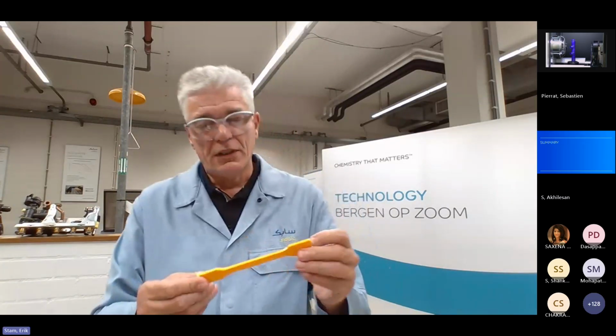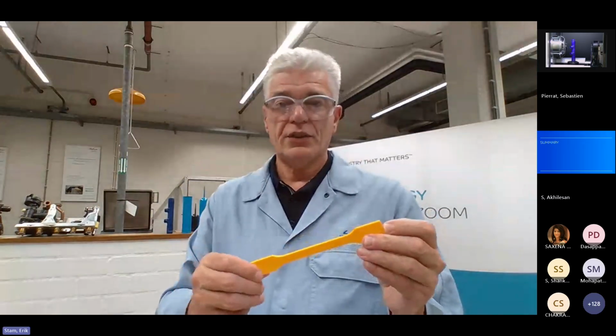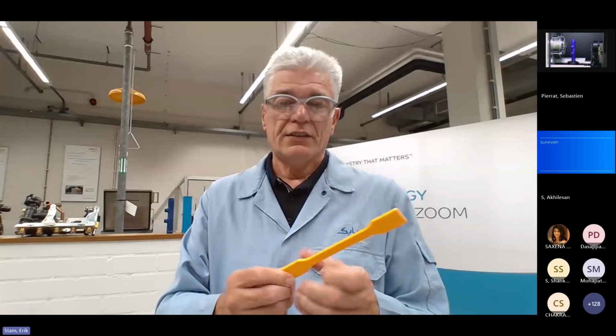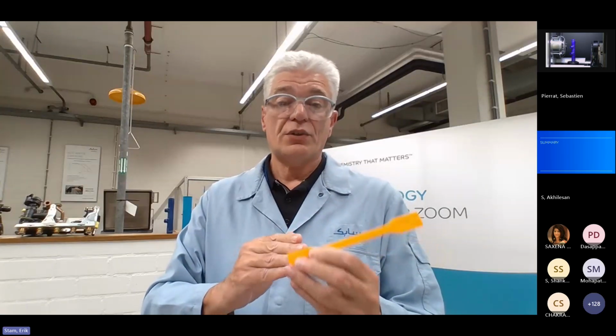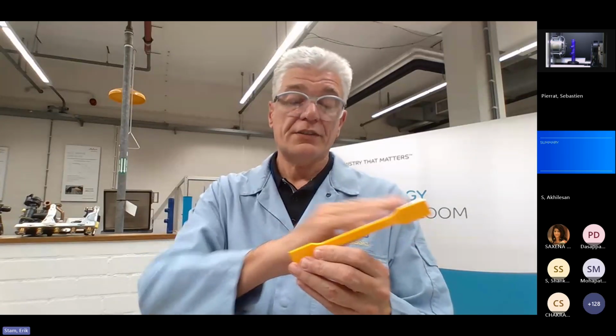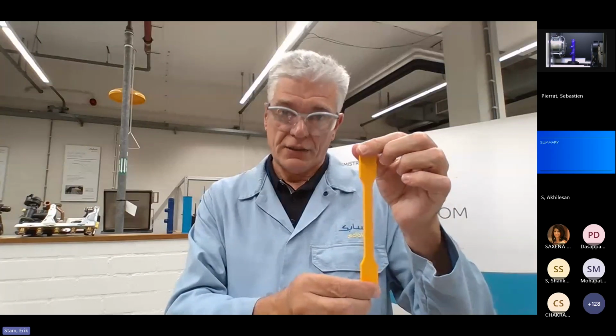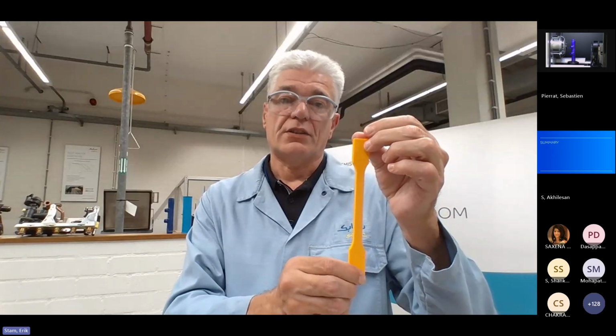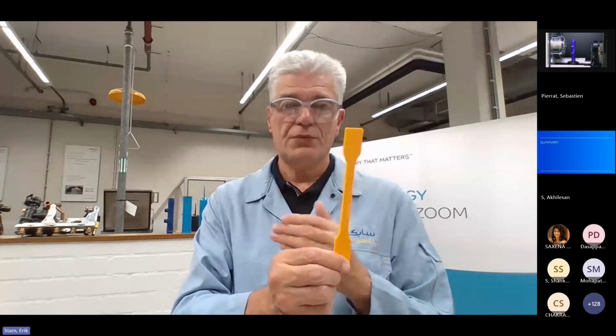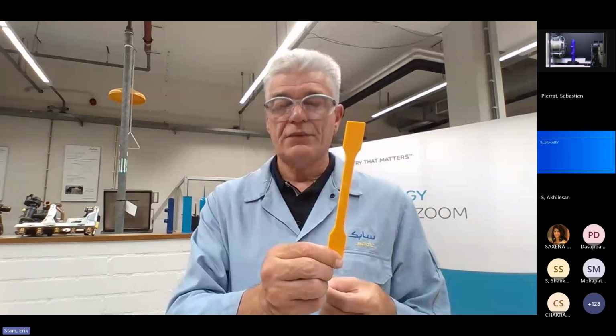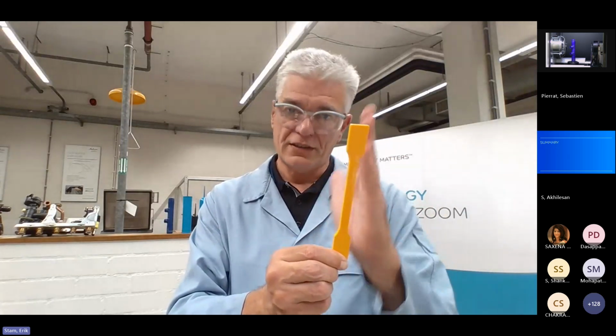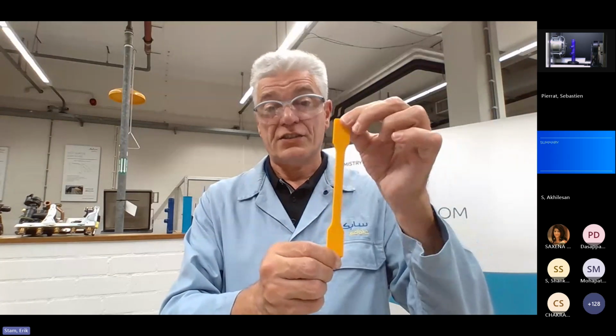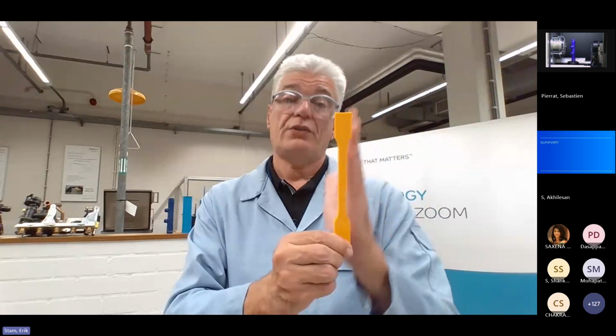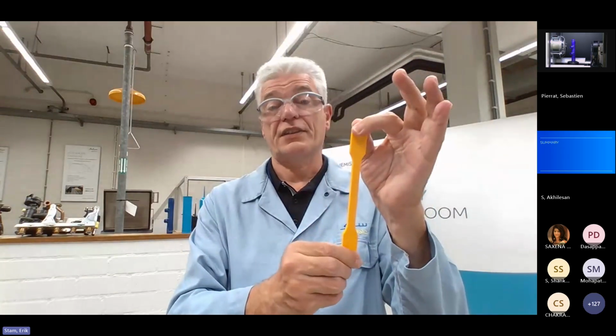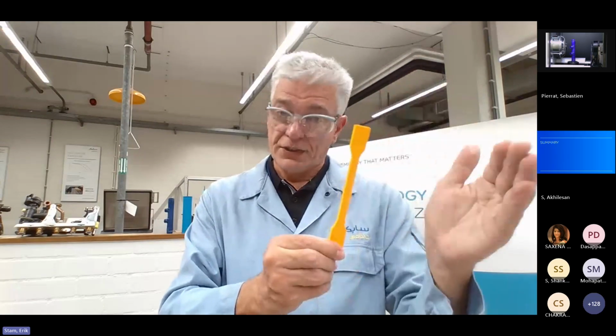Well, first of all, if you look at the tensile bar and you have glass reinforced materials, then you know if you inject it, then the fibers are orientated nicely in this direction. If you then do a tensile test, that means that you get the optimal strength. And this is of course, like I showed you before, in the real application, you will have the fibers in different directions, not always in this direction. And also with this test, you will have only uniaxial stresses, which also is not the case in the real application. So for that purpose, we have different samples in-house.